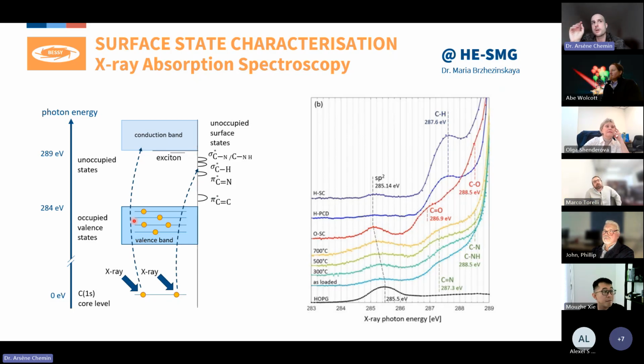Yeah. I mean, if you work with undoped diamond, the charge depletion layer thickness can be huge. So you would reduce a lot the activity of your NV centers just because you remove the charge. At least that's what I expect. If you have an oxidized surface on the other hand, you can expect either a less upward band bending or even a downward band bending, depending on where your Fermi level is.